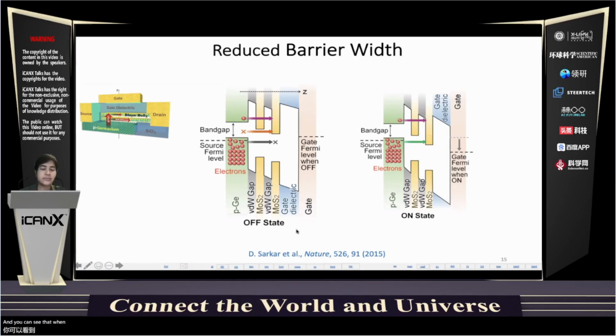And you can see that in the off state of the transistor, the regions in germanium which are filled with electrons do not coincide with the empty regions in molybdenum disulfide. So we have minimal current here. If we go higher in energy, we encounter the band gap of germanium. This is a forbidden gap, so electrons do not stay here. So again, minimal or no current. And then when you go higher in energy, we encounter the conduction band of germanium. Now we have doped this germanium p-type, so the Fermi level is in the valence band. As the number of electrons decays exponentially, very few electrons are there in the conduction band. So again, the current is low.